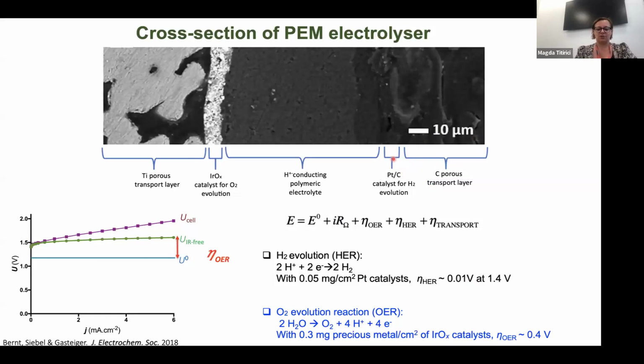carbon at the cathode. Now, if you look at the thermodynamics here, potential versus current, you see that most inefficiencies come not from the hydrogen evolution reaction, which happens at the cathode, and here you need as little as 0.05 milligrams per square centimeter of platinum for a very low potential, but really from the oxygen evolution reaction, where you need quite a lot of iridium catalyst, and you would still get a significant potential.